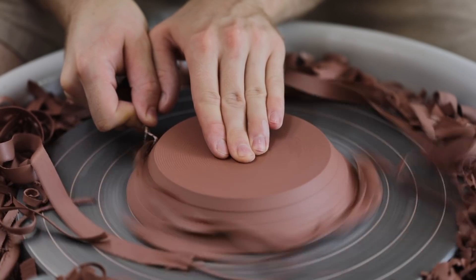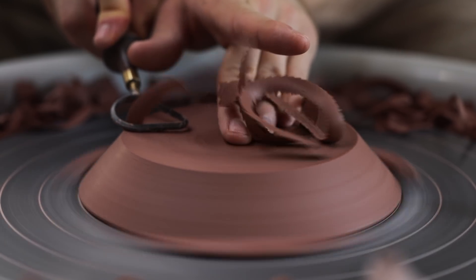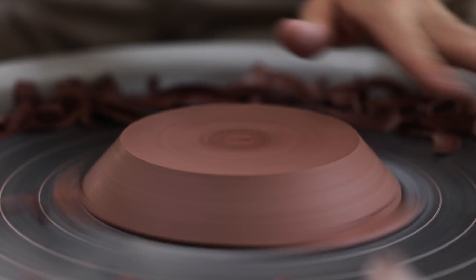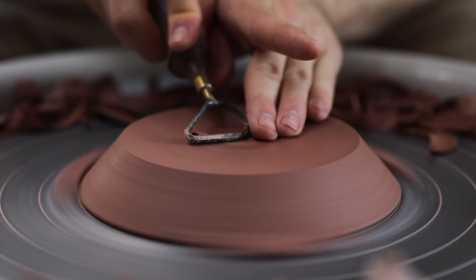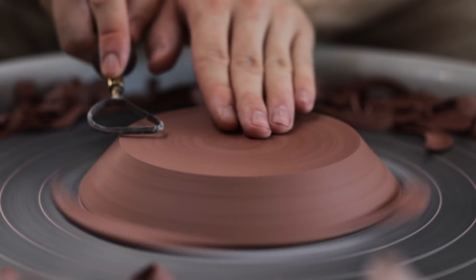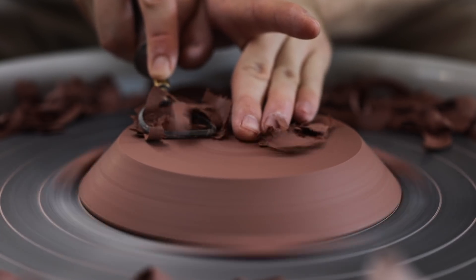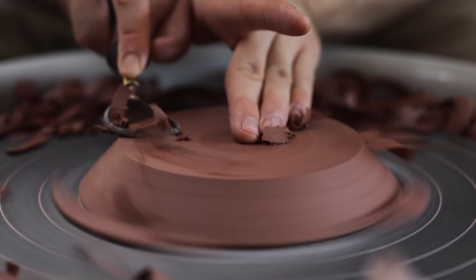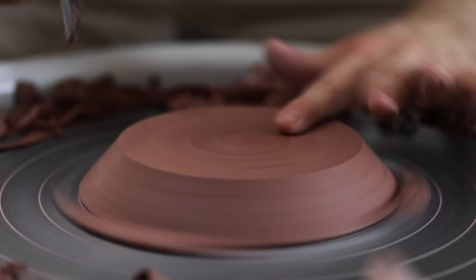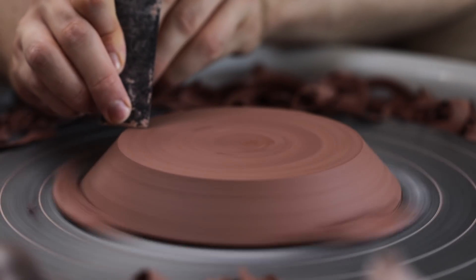It's always a joy when the trimmings fly away like that, and thankfully all of the material removed during this process is completely recyclable. I dump these thin leather hard trimmings directly into water and they turn to a fine sludge in minutes, which can eventually be ladled out onto thick plaster bats where the excess moisture is absorbed. Once the clay is back to the same consistency as a freshly opened bag of clay, you peel it away from the plaster bat and wedge it up — or knead it up, for those who don't know the term — until there are no air pockets left and it's one perfect, even, smooth consistency.